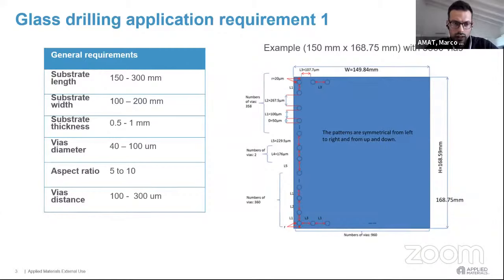I put it here in quite general terms, so you can have just an idea of the basic understanding about this process. And we're looking at substrates which are approximately, let's say, the usual up to A4 size, so maximum 300 millimeter by 200 millimeter. The thickness is ranging from 500 microns to 1 millimeter. And the via diameter for this specific application can be as low as 40 microns and can go up to 100 microns.